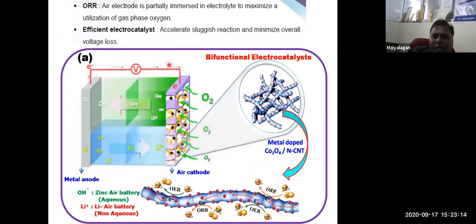The anode is a metal part, and at the cathode oxygen reduction and oxygen evolution take place. You use a catalyst. The anode architecture you need not change, but the major performance depends on the cathode, the air cathode, where oxygen comes in and oxygen reduction and oxygen evolution take place. So this catalyst is much more important to accelerate the sluggish kinetics. So you need an efficient electrocatalyst.